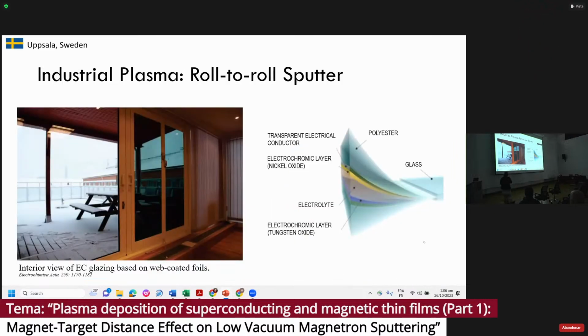So what are the applications of magnetron sputtering? As I mentioned earlier, I was working with roll-to-roll sputtering. We were able to deposit on glass, polymer, and then this polymer is actually sandwiched. We put an electrolyte in the middle, and then these two polymers are deposited with indium tin oxide and nickel oxide, and the other one is indium tin oxide and tungsten oxide. In between that is an electrolyte, and then these things get sandwiched in between the glass. This glass becomes our window. Now, what's the difference between this window and this window? This one is switched off, and this one is switched on. Now, this is how the electrochromic window works. And it was a startup company some 20 years ago, and now it's a commercial company.